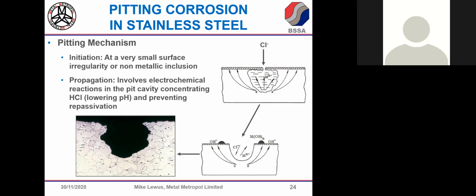And as the pit develops, the concentration of hydrochloric acid gets stronger. So actually, the pitting can rapidly accelerate. Now, a monolithic component, you might be able to live with it, but if it's something like a tube carrying some liquid and the tube wall's breached, well, that's it. Certain components would need replacing straight away.